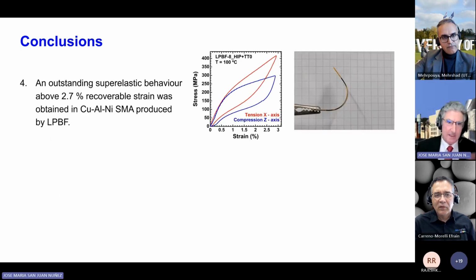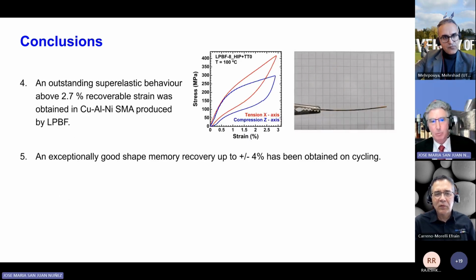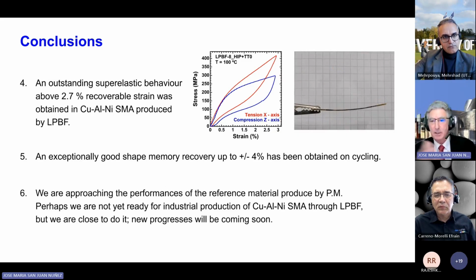So just remember that an outstanding superelastic behavior of about 2.7 recoverable strain has been obtained in both compression and tension in different axes, and good shape memory recovery up to 4% has been obtained on cycling in the material produced by AM. So if we compare with the classical route, we are approaching the performance of the reference material produced by powder metallurgy.